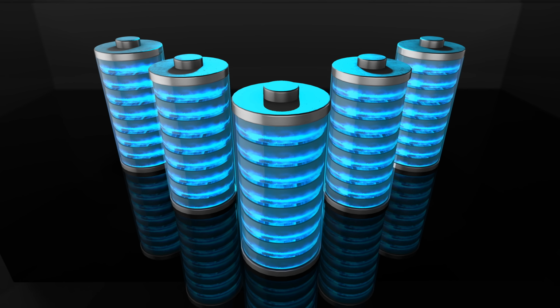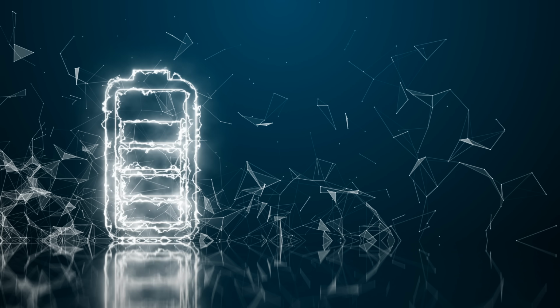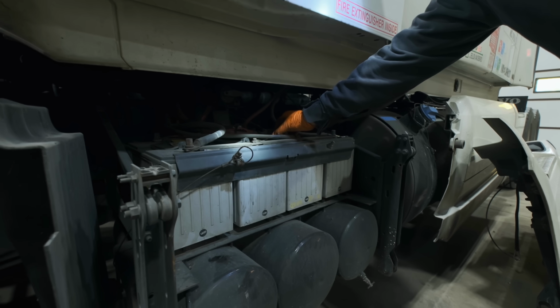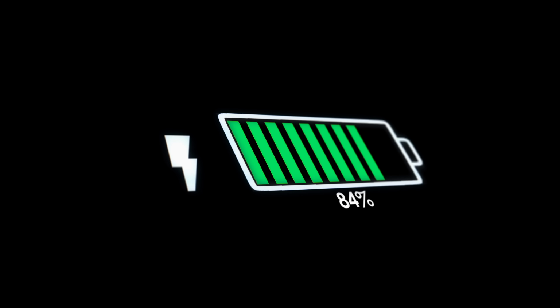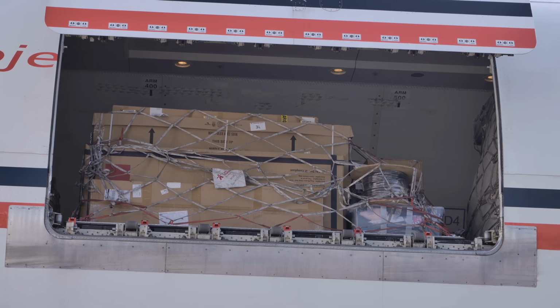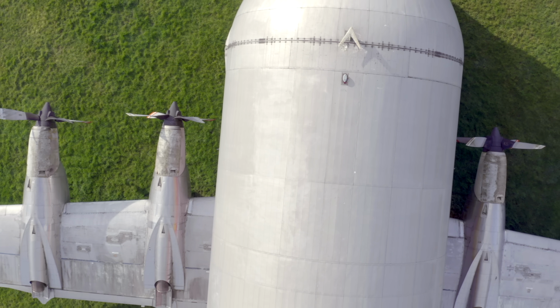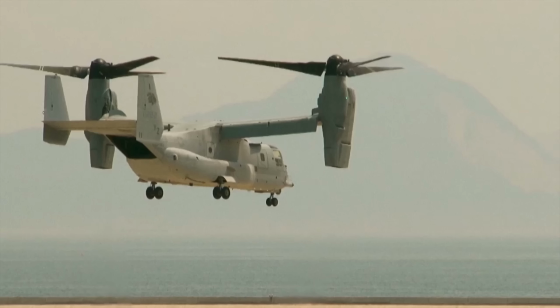Just imagine a battery that's lighter, cheaper, holds more energy, and that will never catch fire even if you crash. But just when we're getting excited about this breakthrough battery tech, we started finding some major drawbacks as well. The solid-state battery's biggest enemy is power density. These batteries generally suffer from low charge and discharge rates, limiting the amount of power we can extract or put back in. And now this is a major problem for aircraft that need an immense amount of power for takeoff, and in the case of VTOLs, for hovering.